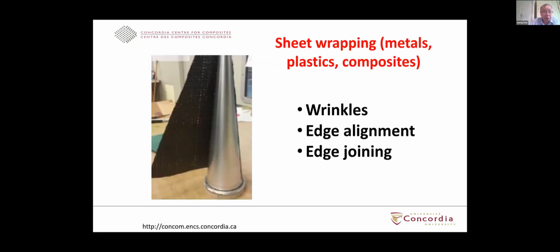In the case of sheet wrapping, the way you do that is that you need to have a mandrel, some kind of mold. The mold can be made out of wood or metal, and it needs to have the conical shape. Then you take a sheet of material, either plastic, paper, or whatever, and you wrap it around this mandrel. After that, you join the seam together. But this technique has some issues: if you don't do a good job, you may have wrinkles, and you have edge alignment, and you have to join the edges together. So that is one technique that people have used in making the conical shape.